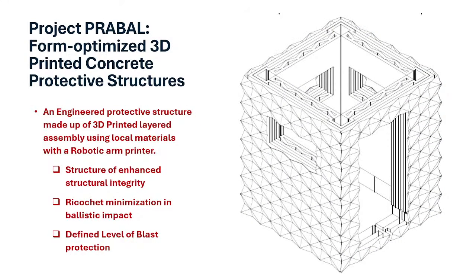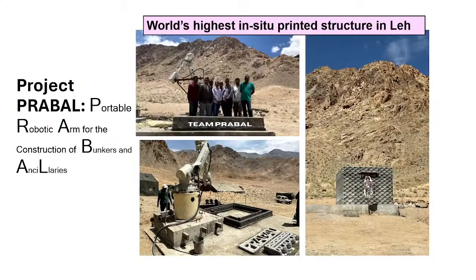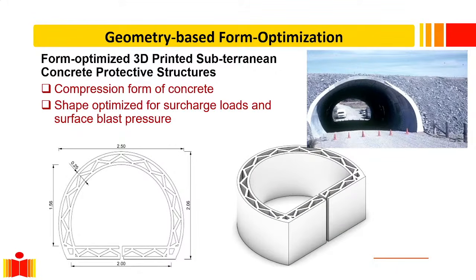The surface features you see are engineered to give high level of ballistic protection. The shape itself has been optimized for a very high level of blast protection. And this is the bunker that was on-site printed. And we're taking this further for geometry-based optimization for developing these subterranean protective structures, where we come up with this geometry which is eggshell shaped. Basically, the entire structure goes into compression.